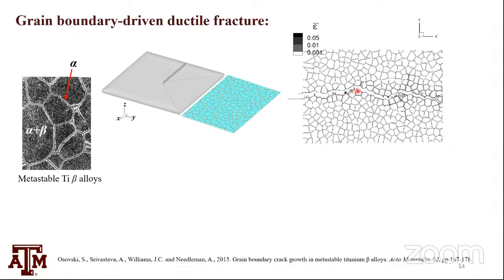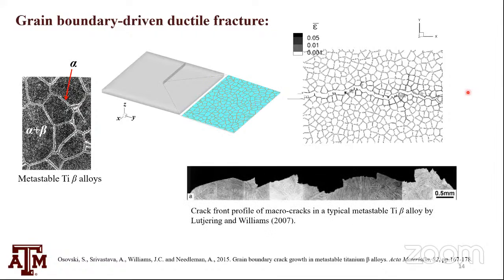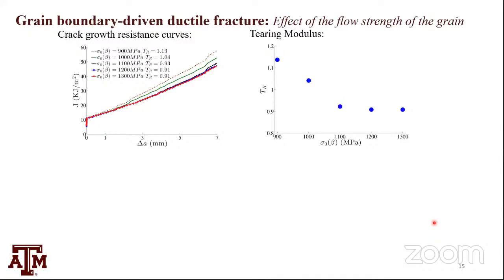These hair-like features are visualization errors, so we just ignore them. And we get realistic crack paths like what you would see in experiments. The crack follows the boundaries of the prior beta grains along basically the alpha grain boundary alpha. And we could extract J-delta-a curves from this simulation.